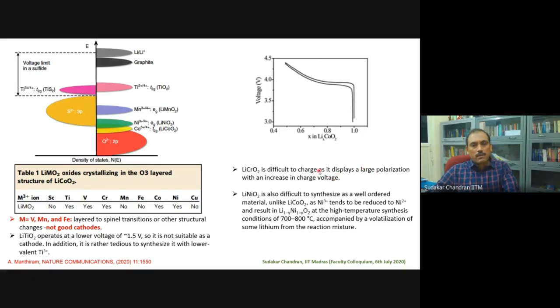Polarization means it is very difficult to put the charge in and out, so it introduces large resistance to the charge transfer. So that was not possible. And then nickel had a problem of oxidation. It would always get reduced, and then lithium goes away during the high temperature synthesis. And the only compound they could find was LiCoO2. It was like a magic compound. So of course it came out of hard work.